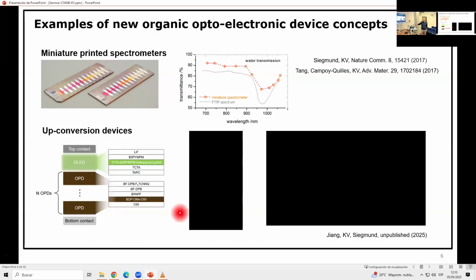The other thing we recently started doing, well, maybe before I talk to this, is printed, but you can also deposit organics using vacuum deposition. And so then you evaporate the molecules and they deposit on a substrate. The nice thing about the vacuum deposition is you can do 20, 30 layers on top of each other without dissolving the bottom layer. And each of these layers, the thickness you can tune very precisely, because with vacuum deposition, it's easy. So we can tune this thickness within a 1 nanometer error margin. So here is a device which has 35 layers, I think. For a physicist, this is fun. I mean, if you can't make your own molecules, at least we can stack 35 layers of each 20, 30 nanometer. It's a simple device.